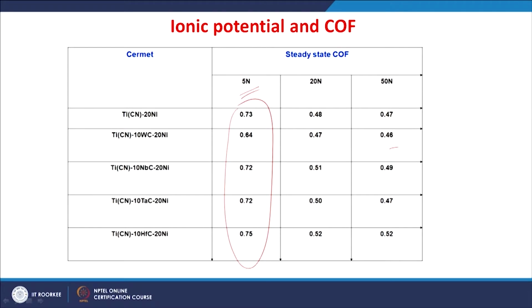Now, among the investigated cermets, even at a lower load of 5 Newton, you can see the minimum coefficient of friction was obtained for the cermet having tungsten carbide, whereas the maximum coefficient of friction is obtained for the cermet having hafnium carbide or for the baseline cermet. There is not much difference here, but overall, at lower load the coefficient of friction is high, whereas at higher load it becomes less. So, it indicates two load regime conditions, a higher load at 20 or 50 Newton, or a lower load of 5 Newton, where the friction is changed.